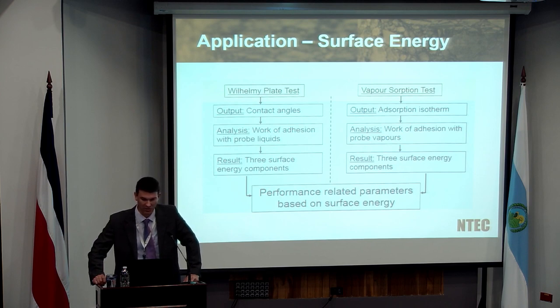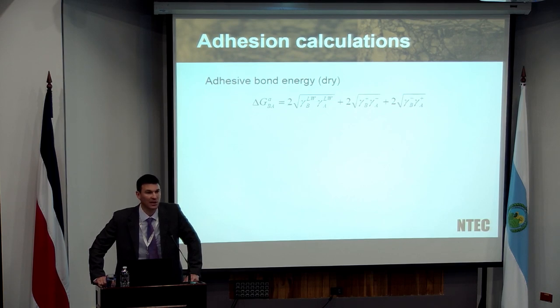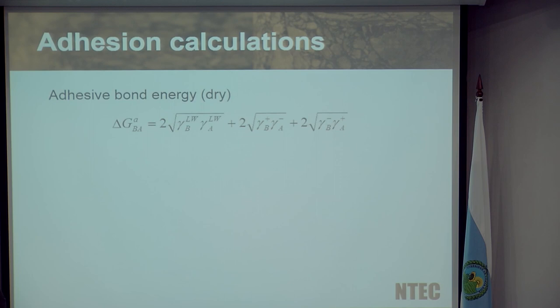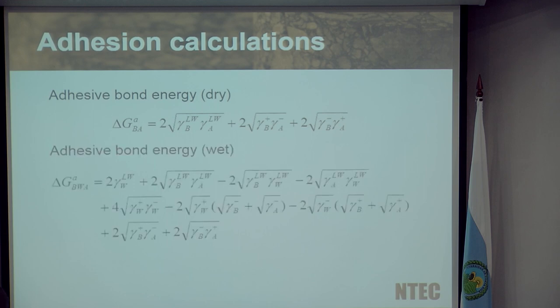And again, there's some clever maths, which I'm going to show you in a second, where we take the individual components in terms of the surface energy of the bitumen, the surface energy of the aggregate, and we can work out how much bond or how much adhesion we can obtain between those two materials. And the equations that we're going to have, again, I'm not going to spend too much time going through them, but effectively, we have a combination of the polar materials tend to want to stick together. So your acid bases want to stick with acid bases from the second material. So whether it's a bitumen with a stone, it will depend on where the individual components are. Obviously with bitumen, non-polar components are quite significant, but increasingly, obviously with the aggregate, you have to take into account the polar components. And you get a very simple equation for the energy of bond in the dry condition. That equation then becomes a lot more complicated when you introduce water. So far what we've talked about is just measuring the properties in terms of surface energy of our two components. Now I'm starting to introduce a third component.